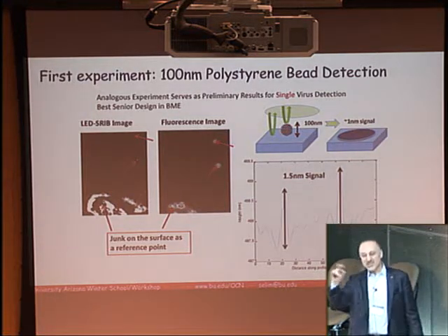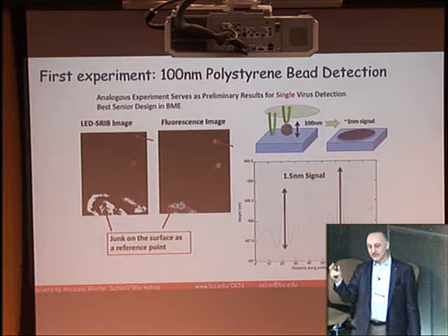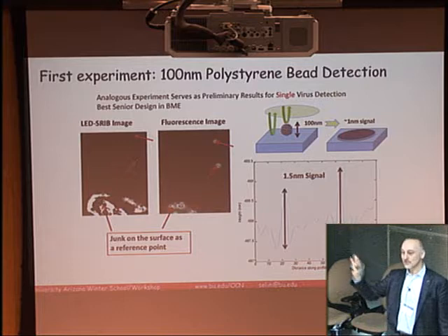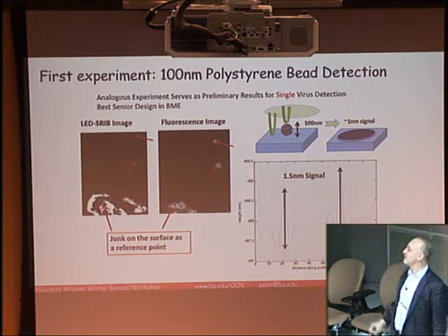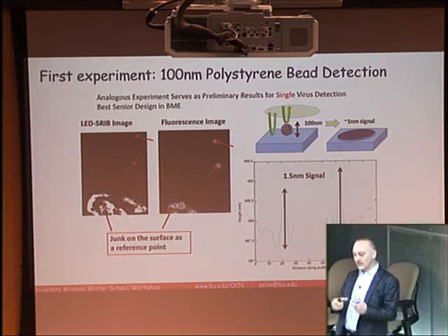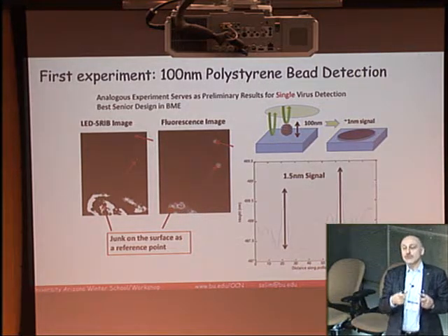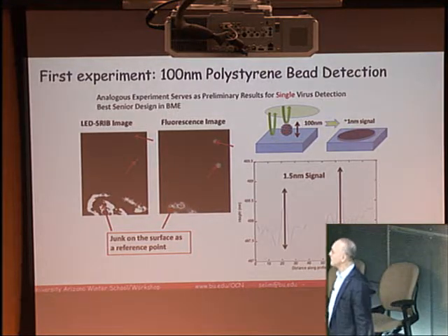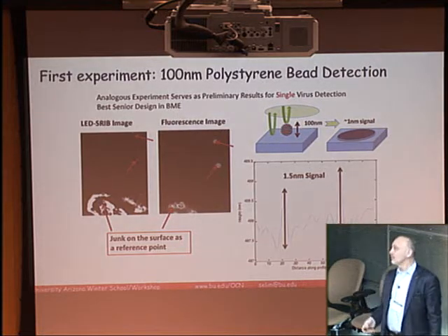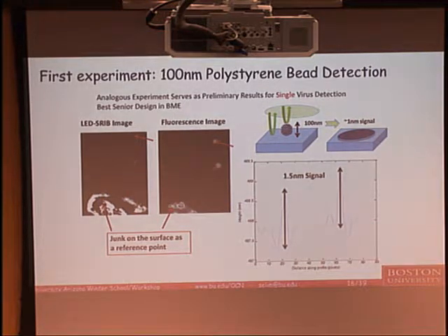If I'm doing a thickness measurement, which is a picometer capability, not attometer or femtometer, just a picometer, using a very simple soap bubble like silicon wafer, and I have a virus, and I get my optical magnification good enough to have a 1 micron resolution, which is trivial for visible optics, that 100 nanometer virus will provide me about a nanometer signal. So without any scattering model or anything like that, it's just the back of the envelope. Let's say this should be visible.